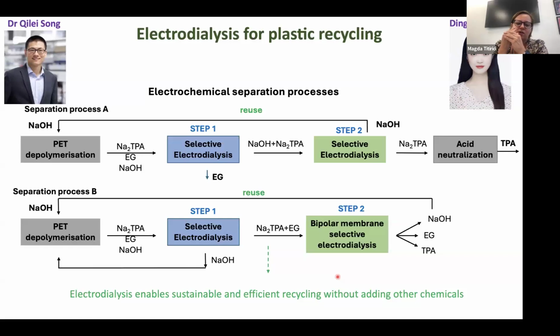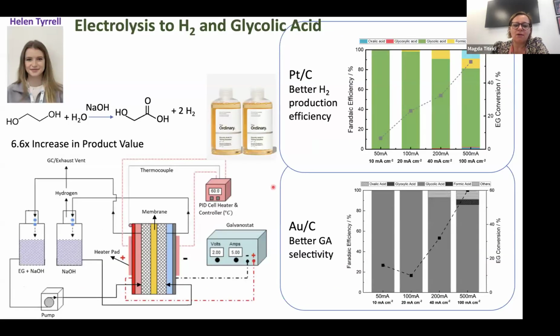And we have 2 different ways of doing it. One is with 2 different membranes. So one is with 1 membrane and 1 bipolar membrane. And we separate nicely and efficiently all this, but I don't have time to tell you in detail about all these processes. And then once we separate everything, as I said, we take ethylene glycol, we put it to an electrolyzer, similarly to what we do for glycerol, and we make with quite high efficiency glycolic acid out of this.